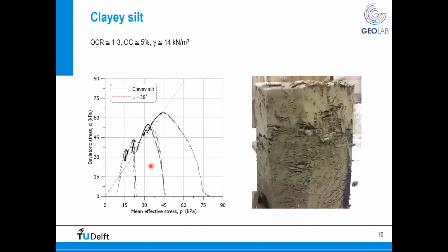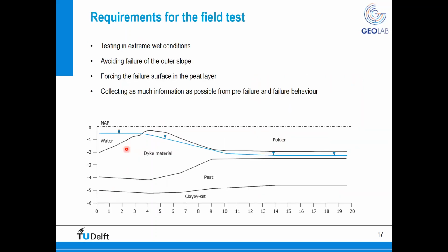And then eventually moving downward towards the clayey silt material, which is the layer underneath the peat. This material has a friction angle of 38 degrees. It has a much higher component of clay compared to silt, so you don't see this dilation accompanied by an increase in the deviatoric stress. But you clearly see a more standard, let's say, response. So you have an initial elastic phase, you touch the yield surface, and then basically you have softening towards large strain. So from this perspective, we have somehow characterized the behavior of our material at the laboratory scale, and we were also able to clarify the layering inside our subsoil.